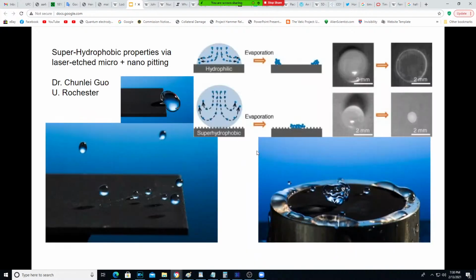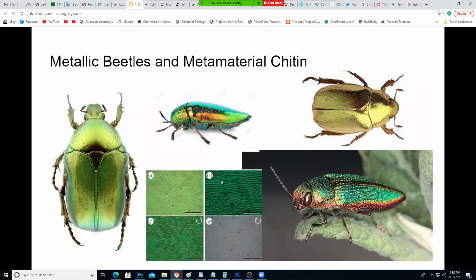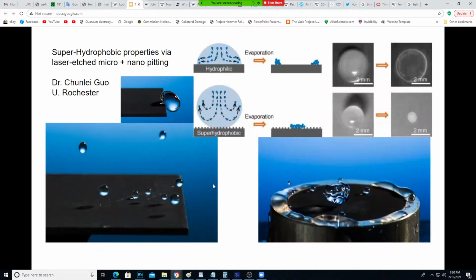This is great. So we find out that if we etch, University of Rochester, a guy named Dr. Chunlei Guo is doing research into materials, and he found out that if you etch these materials with a laser, do laser etching, micro and nano pitting, similar to the nano pitting on the bugs, but you try different patterns and different shapes, which we've learned from looking at the bugs. This one makes gold, this one makes this iridescent green and whatnot.